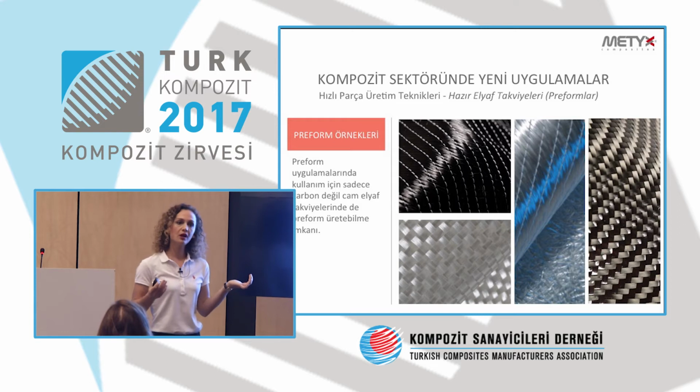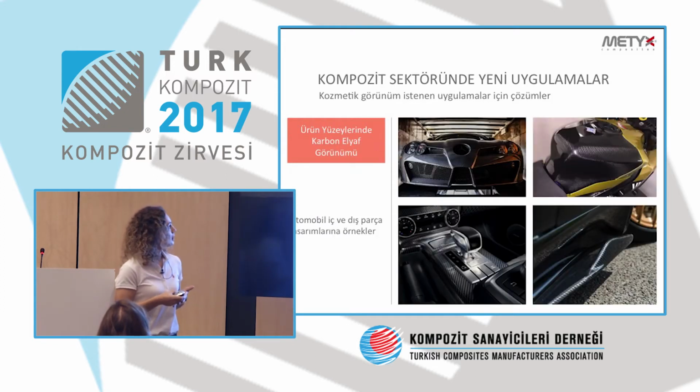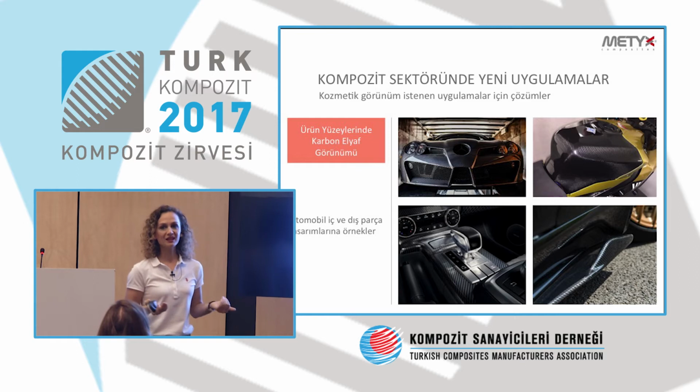But there's something that you need to pay attention to. The resin that you're going to implement later on has to be in harmony with the resin that you're using with the adhesive. Otherwise, due to the mechanical differences, some failures might occur, and that's the reason why we give some certain recommendations about what type of adhesive to be used. One other thing is the cosmetic view of the parts.